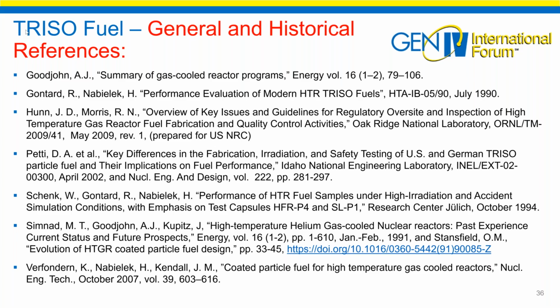Okay, all right. I'm the fuel fabricator for TRISO fuel. First of all, I would need to demonstrate that my fabrication method is stable. I have tight tolerances. I know what I'm doing in terms of QA, QC on the fuel. Let's say I have the Northeast flux trap, and I'm making compacts. I would have my fuel in the reactor for about 2.5 years, let's say at 15 weight percent. That's about how long our irradiations last, and it would take about 2.5 years to do that.